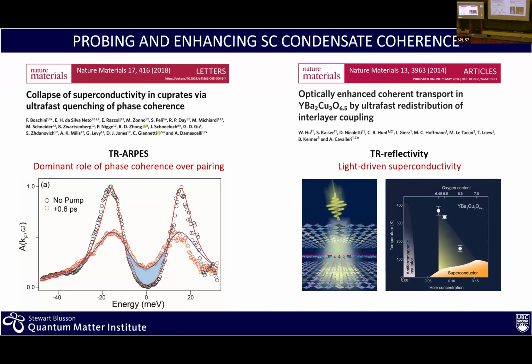And another way of using these approaches, which is highly debated but very interesting, is done by Andrea Cavalieri, Max Planck Hamburg. It is coming in again on these superconductors, now pumping them with an energy which is resonating with some of the optical phonons in the system, so the lattice vibration. And what they believe they see is an enhancement of superconductivity from these numbers almost all the way to room temperature. So this is what would be light-induced superconductivity. So it's another big branch of work in a quantum material direction where you really drive new states of matter optically or in cavities. So there is really one range of possibility.